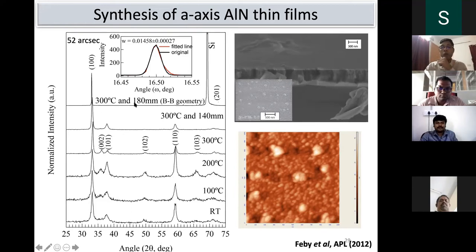This one is powder XRD. The difference is, in the case of oriented film, the GA XRD may miss the peaks because of the orientation. But in the case of powder XRD, both arms are moving, the incident angle and the detector side. Because of that, you can capture that one particular orientation very well.